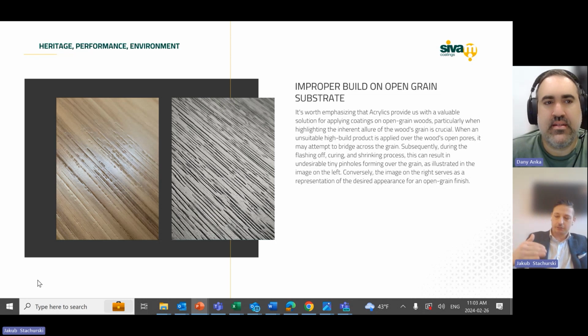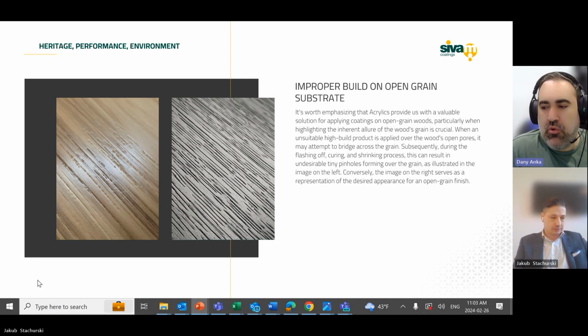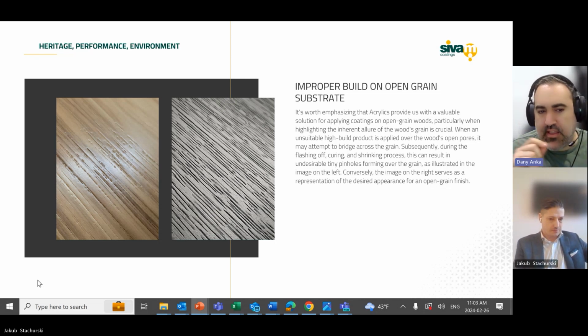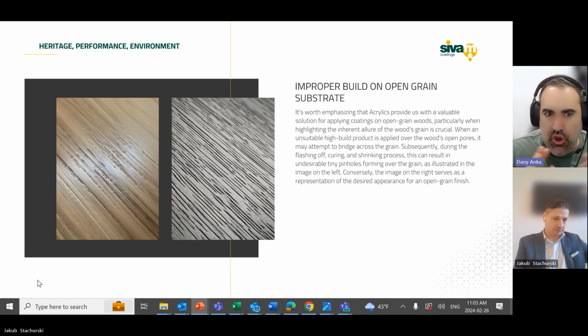So it kind of depends on the manufacturer and the formulation itself. But definitely acrylic will be the water white, non-yellowing, high clarity, lower build in most cases, and highly flexible product. Right, because I guess acrylic will be used, for example, if I stain the top of a guitar and I want to really keep that color that I achieved non-altered, I will have to use acrylic, for it to not go a little bit brownish or pop more the color. Correct. Okay, that was amazing. Now it's so much clearer.